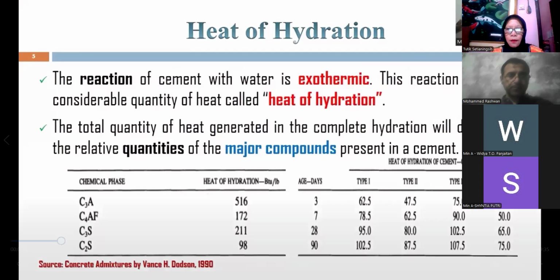For example, as you know, the cement is composed mainly of four major compounds: C2S, C3S, C4AF, and C3A. Each one of these compounds liberates a different amount of heat. For example, C3A liberates the highest amount of heat during hydration, about 516 BTU per pound. BTU means British thermal unit. And the lowest one is C2S, which liberates 98 BTU per pound.